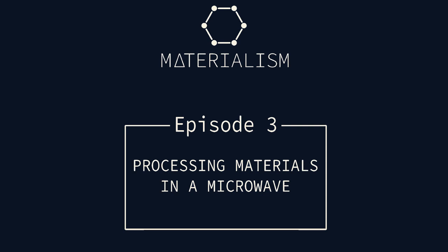Yeah, so one thing that is very critical in microwave processing is little things like where do you place your container inside the microwave oven? Since we're talking about a multi-mode instrument, the microwave radiation is not equally distributed inside the chamber. Very much like your kitchen microwave, this is why you have the turntable, right? Because you want to even out hotspots. We're usually not using a turntable, but we make a big deal out of placing our reaction setup at the exact same spot. If you do that, you get reproducible results.